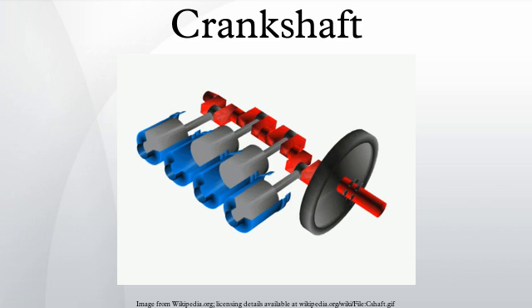Fatigue strength. The fatigue strength of crankshafts is usually increased by using a radius at the ends of each main and crank pin bearing. The radius itself reduces the stress in these critical areas, but since the radius in most cases is rolled, this also leaves some compressive residual stress in the surface, which prevents cracks from forming. Most production crankshafts use induction hardened bearing surfaces, since that method gives good results with low costs. It also allows the crankshaft to be re-ground without re-hardening. But high performance crankshafts tend to use nitridization instead.